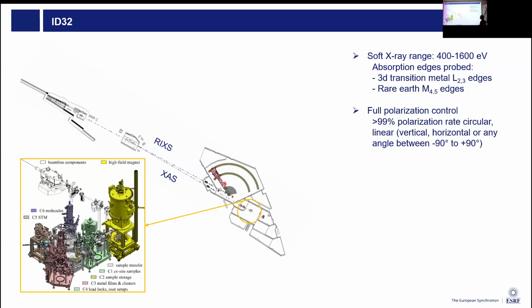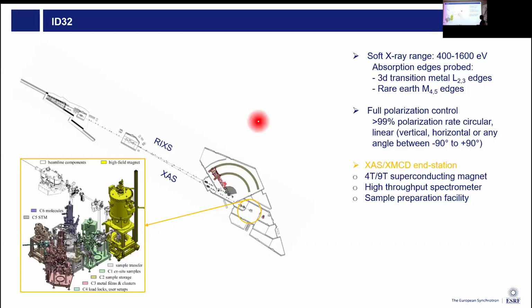Our first X-ray end station I want to talk about is the XAS one. And this, we have a superconducting magnet shown in yellow. We have the option of 4 Tesla perpendicular to the beam, 9 Tesla along the beam, so we can do dichroism studies. There's a small high throughput spectrometer that I'll talk about a bit later, as well as our sample preparation environment, where we have chambers for depositing molecules, chamber for depositing metals. You can do STM, PEM, to check the in situ growth of materials. The idea is that if you have a delicate sample that you want to prepare on site and then transfer inside ultra-high vacuum for the experiment, we're capable of doing that.